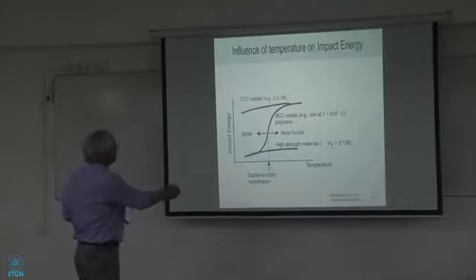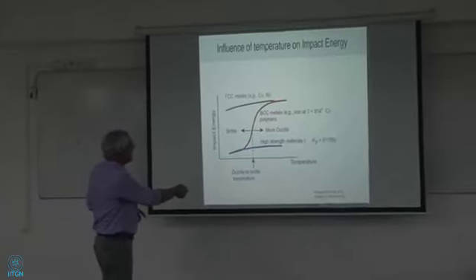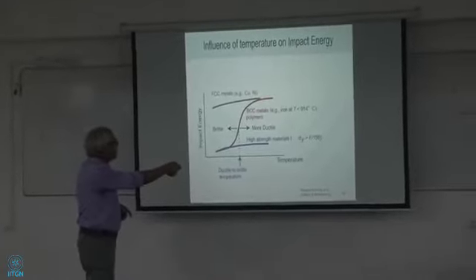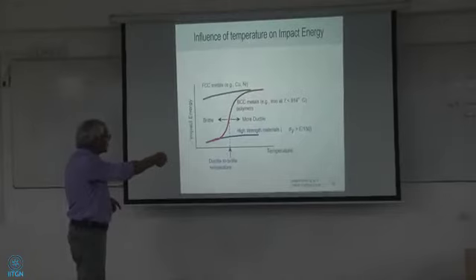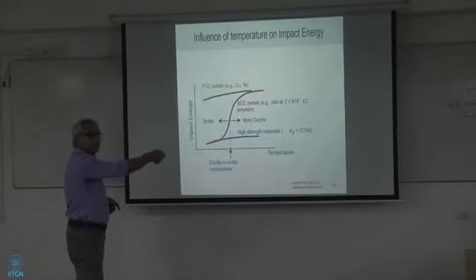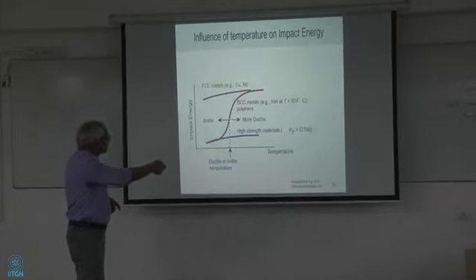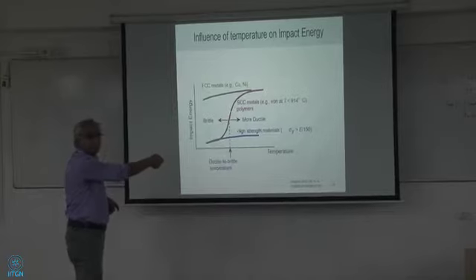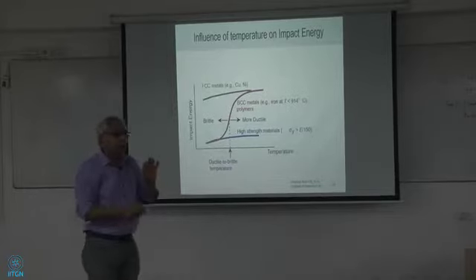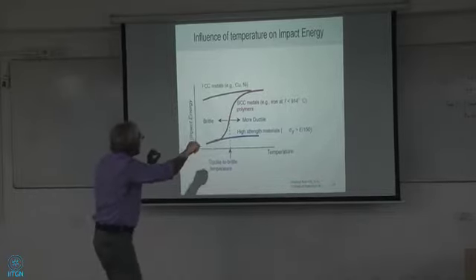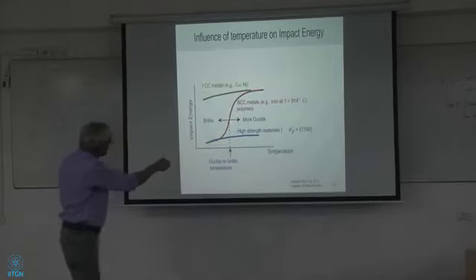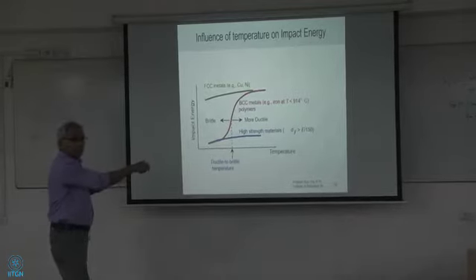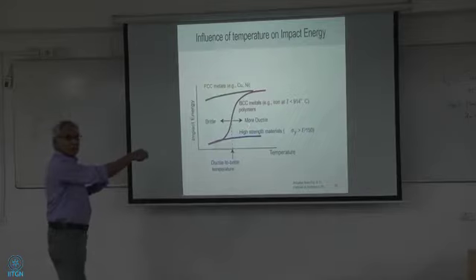What will happen is that in the case of body-centered cubic materials, most often you get a curve like this, very well defined, like an S curve. Right here is the inflection point, where the curvature changes. Here the curvature is up, here the curvature is down like this. So the inflection point is right there.